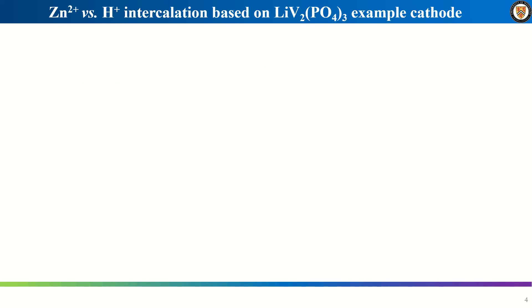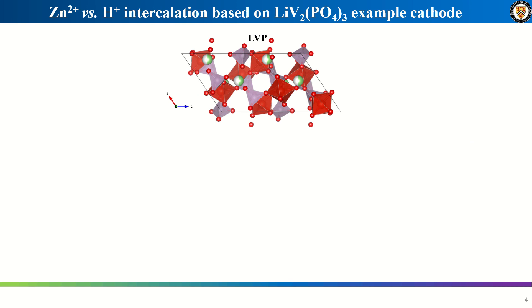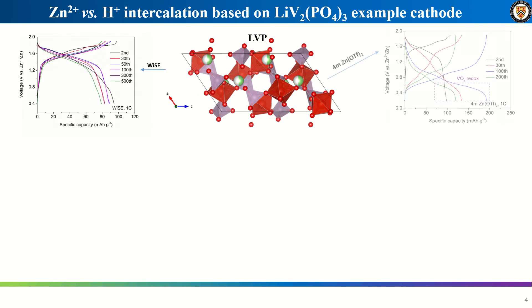In my research, lithium vanadium phosphate, or LVP, was used as an example cathode. Its electrochemistry was tested in both zinc triflate and a water-in-salt electrolyte. As you can see, in zinc triflate, a 0.5-volt plateau gradually appears and becomes longer when charging-discharging continues, indicating the increasing proton intercalation. In contrast, in the water-in-salt electrolyte, there is an absence of this plateau.